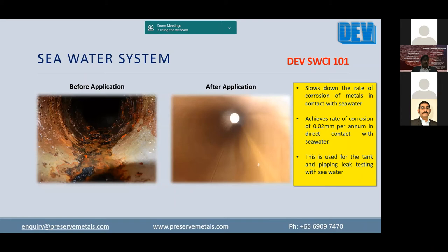Another area is the tankages, where the clients do the hydro test. They use seawater because of the huge volume required. And after the seawater is drained, the chlorides on the bare metal of the internal walls start to corrode the tanks.